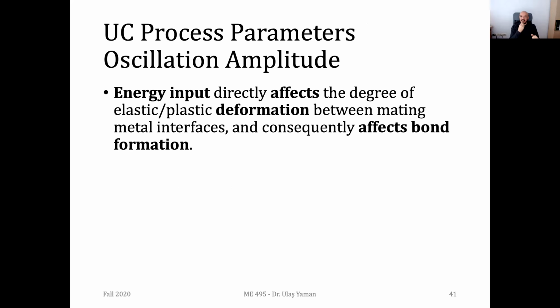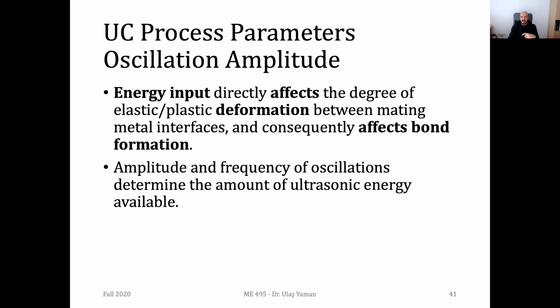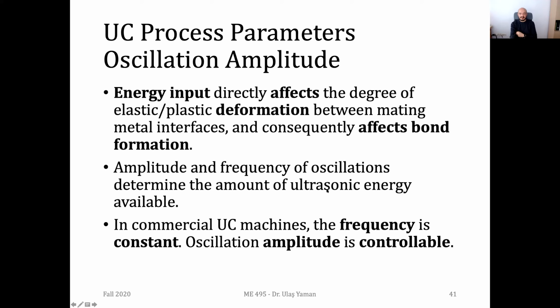Let's have a look at the first one, the amplitude of the oscillations. As I mentioned, the energy input is quite important, so this level should be above a critical value. Otherwise, you'll not be able to start a deformation and the metals will not be joined together. The energy is affected by the amplitude and the frequency of these oscillations. So it's an important parameter, defining the ultrasonic energy we have in our system.